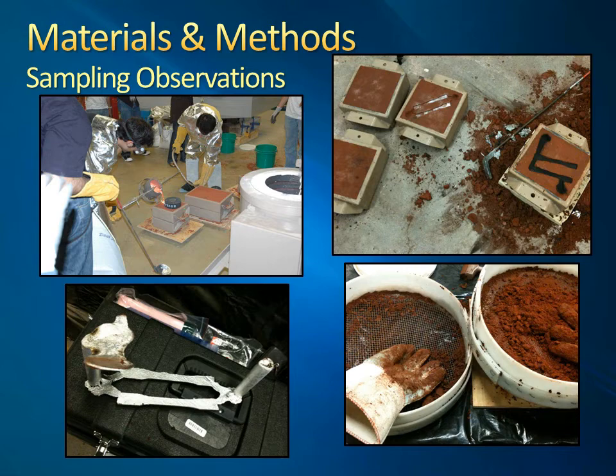The furnace was also set for a temperature of 1450 degrees Celsius, much higher than the 660 degrees required to melt the aluminum. This was done to have the aluminum pieces melt quicker, but also increased the possibility of multiple variants of crystalline silica forming. At the start of the pour of the molds, a large amount of whitish smoke was emitted from the mold. This smoke possibly included metal fumes and silica particulates, along with carbon soot from the heating of the mineral oil included in the green sand. This odor was strong and stale.